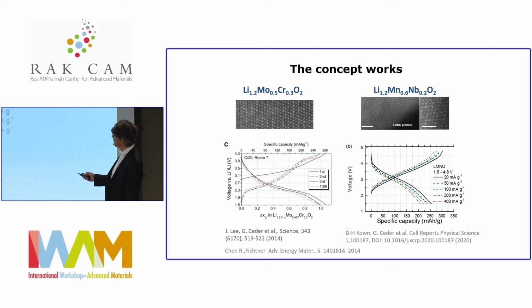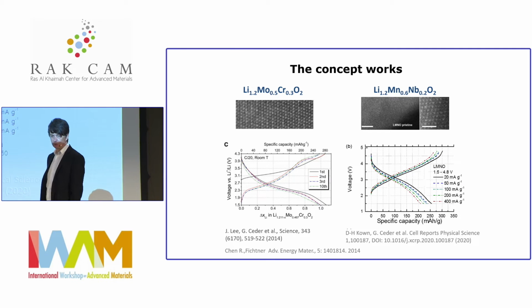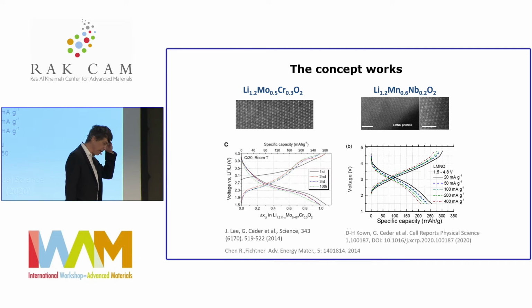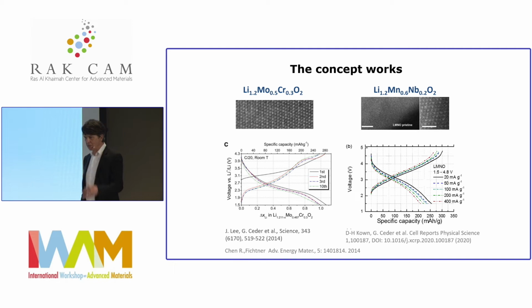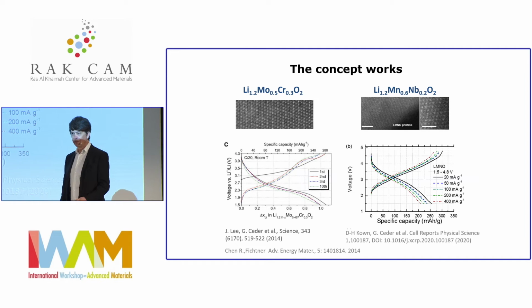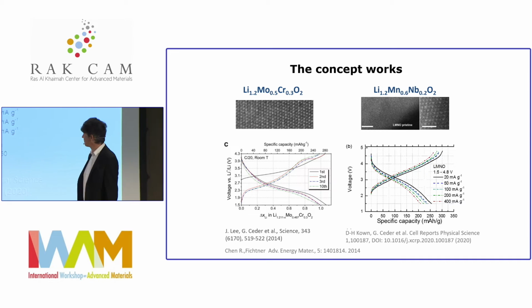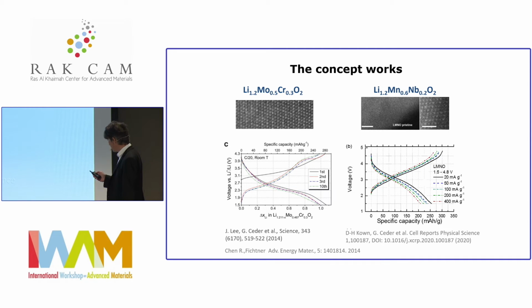Here's actually a STEM of a material that is fully disordered rock salt, but you can remarkably well cycle lithium in and out. This is cycling almost 1 lithium per formula unit in and out. And I gotta say, this was such a surprise to many, including to us, that this is one of those things where when the student comes to you, you say, you must be wrong, this cannot be. And I made him redo it, and it was the same answer. Okay, so that's when we did the theory.